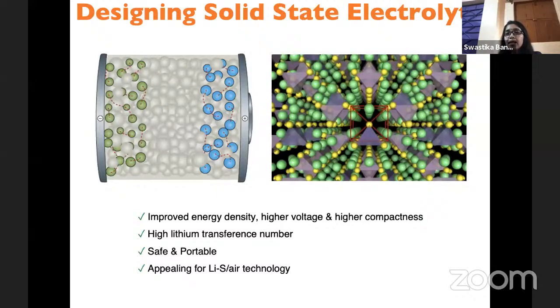So it's an excellent concept that we can replace the liquid electrolyte, which is the conductor for the ions, with inorganic materials, which are solid crystals. With this strategy, we can achieve improved energy density, higher voltage, higher compactness, and a high lithium transference number, because you have no scope for transport of the anionic species. You just have the cationic species.